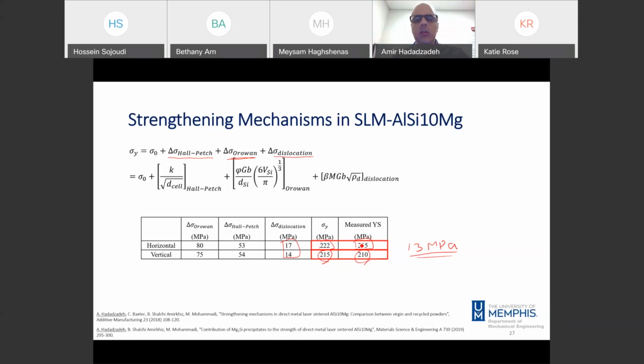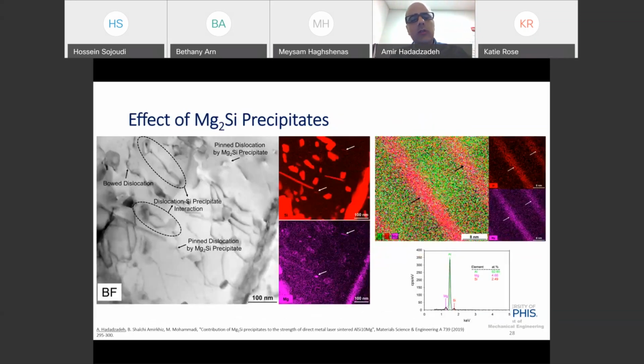To address this difference between the predicted value and measured value for the horizontal sample, again, we took a closer look at the structure of the material using TEM, and I was able to find traces of Mg2Si precipitates in this material. So again, this is a deformed structure. We see the interaction of precipitates or dislocations with the features, over here in the bright field. And one of these features is Mg2Si, as you see them here. And also we're able to confirm that by EDS.